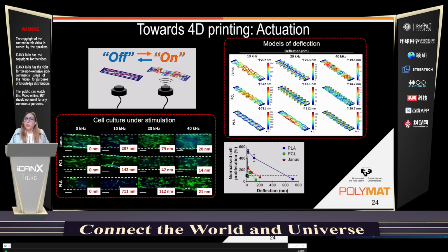And what we observed is that the higher the frequency, the smaller the amplitude of the deflection, right? But what we also observed is that this amplitude of deflection will depend on the material that we were using, so on the mechanical properties of this material. Having PLA the highest deflection, the lowest PCL, and Janus having a behavior in between these two.